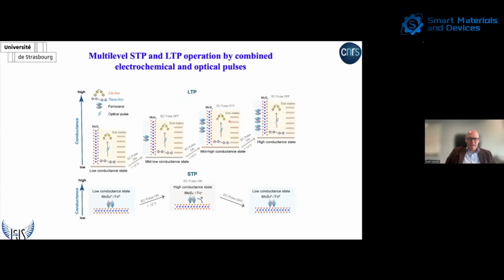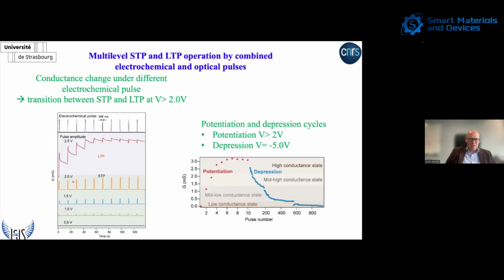And then what we are going to use, and here is just the cartoon, is that if we use low voltages, below 2 volts, with each pulse we trigger the oxidation of the ferrocene to ferrocenium, and then when the pulse is off, it goes back. Instead, at higher voltages, with each pulse we have the adsorption of this ferrocene at the very interface. You can see 1, 2, and 3 molecules that are adsorbed at the interface, with the fine-tuning that comes from the azobenzene states. And you can see here the result: at low voltage, up to 2 volts, we have a very short lifetime of the new state that is created. At higher voltage, we have a much higher lifetime, which is a potentiation process, and we have depression, so we can erase our memory by applying -5 volts, changing the polarity with a much higher voltage.